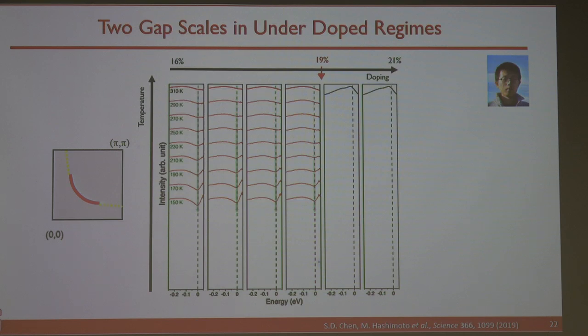Remember, we are measuring at high temperature. Okay. That means at a finite temperature, you can see things above the Fermi level because they are thermally populated. Okay. So that's that. Now I hope you will see the gap energy scale is much larger than the superconducting gap, it's about 100 meV. It's a very poorly defined gap.